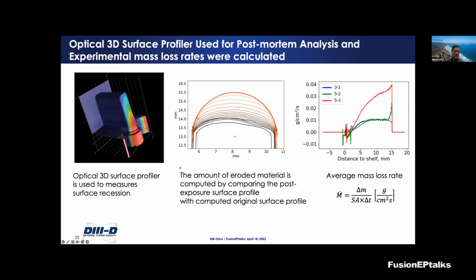We could also take those rods out after the experiment and analyze them in the post-mortem analysis. For that, we've used the optical 3D surface profiler to measure the exact surface recession. This figure in the middle shows in the red line the original round shape of the rod that we stuck into the plasma before the experiments. The next set of lines, brown to black, shows the measurements of the rod by the optical 3D surface profiler, and we can see how much material eroded as a function of distance, and we could calculate the erosion in grams per centimeter squared per second for 3 different rod types.